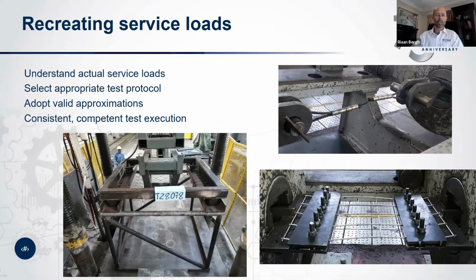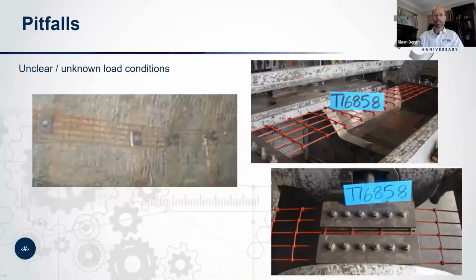So the photo bottom right shows a typical test fixture setup for a welded mesh test that does not approximate the boundary conditions very well. And similarly, on the next slide, one can see on the right-hand side, these tendon straps are fixed into the test machine jaws at each end with a clamp mechanism that ensures that the tensile force is more or less evenly distributed across all 5 of the rods of the strap.